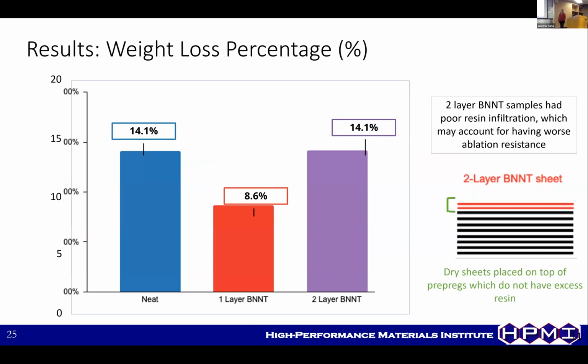Here are some, I guess maybe surprising results. This is the weight loss percentage. We also assumed there may be some added benefit of having less weight loss, or less bulk lost from this ablative testing. The neat lost 14.1%. 1 layer had significantly less weight loss, but the 2-layer had about the same. Upon optical microscopy, we noted that the 2-layer had some dry surface layers that then peeled off, which contributed to this additional weight loss. We're planning on fixing that by increasing the matrix content in the surface to better adhere the surface to the structure.